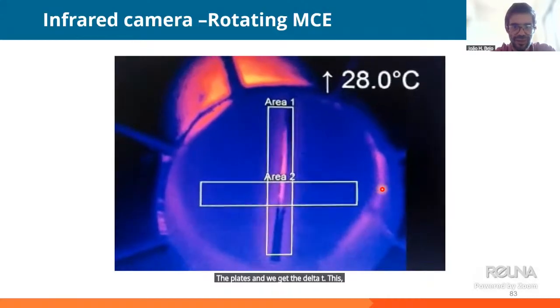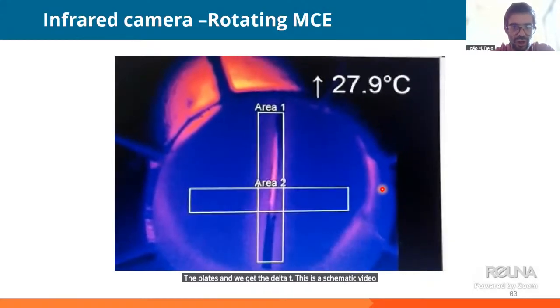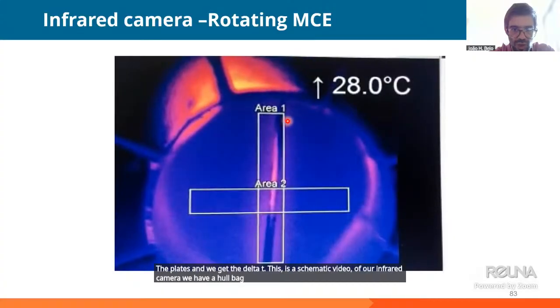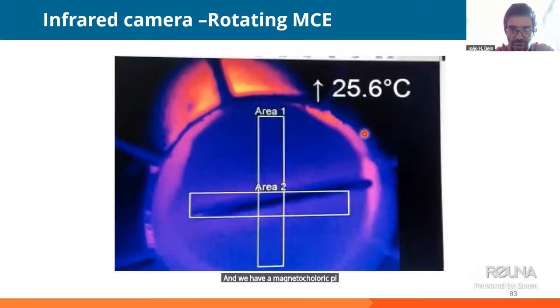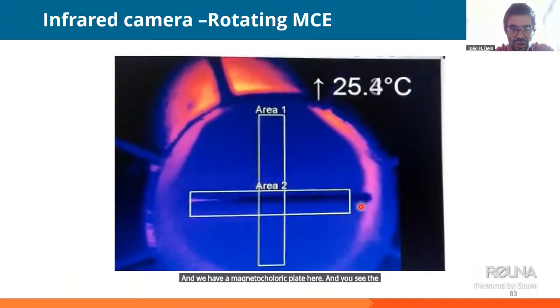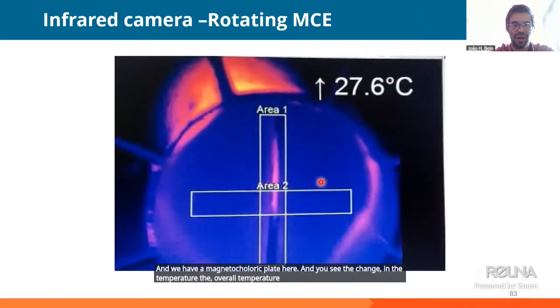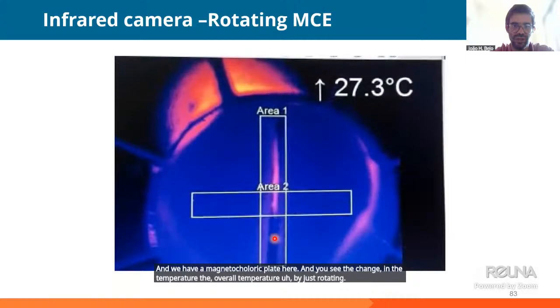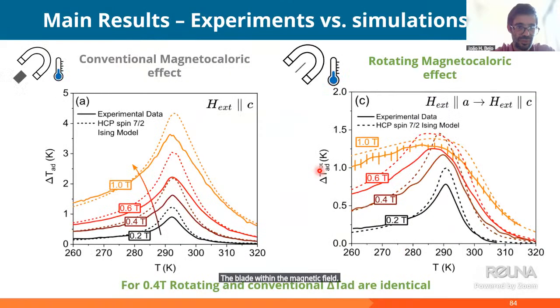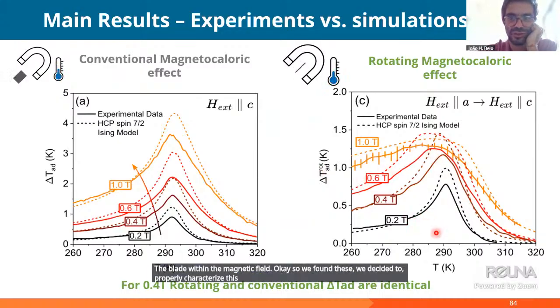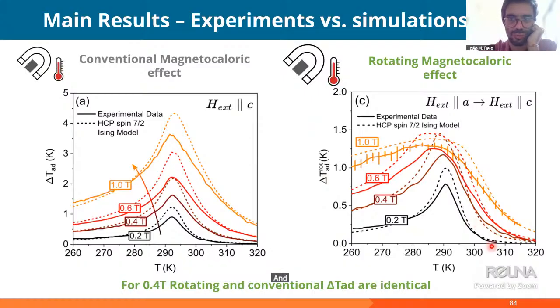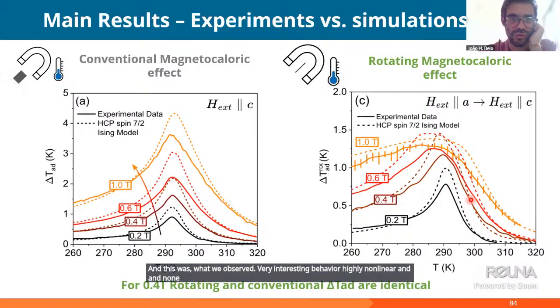This is a schematic video of our infrared camera. We have a Halbach array here, and we have a magnetocaloric plate here. And you see the change in the overall temperature by just rotating the plate within the magnetic field. Okay, so we found this, and we decided to properly characterize this effect for different field intensities, and this was what we observed. Very interesting behavior, highly non-linear and seems non-monotonous.